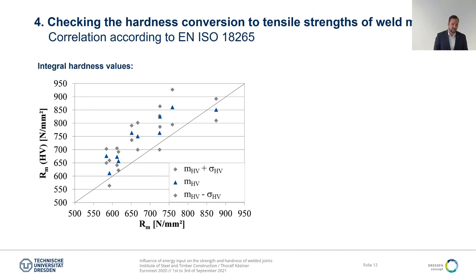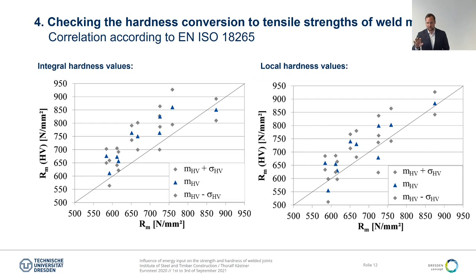So what we can see is that we have a large scattering and that there's not such a good correlation with our test results. So therefore we decided to have a closer look and just take into account the hardness values which were in the failure area of the weld. But what we can see here is also that there is not a good correlation at the end.